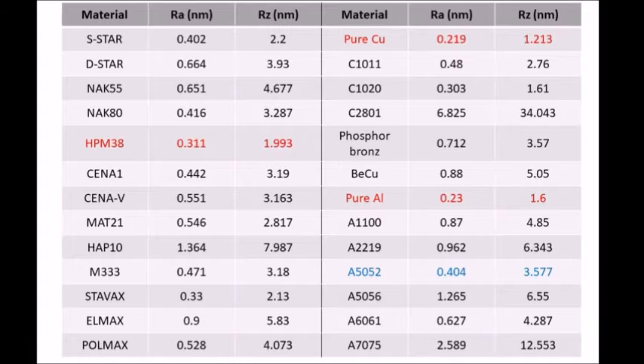In the second page of metal, we have plastic mold steel. The best roughness in this section is HPM 38. The roughness is Ra 0.3 nanometers and Rz 1.99 nanometers. The next section on the right page is copper, and from this section, pure copper has the best roughness. Ra is 0.219 and Rz is 1.213 nanometers.